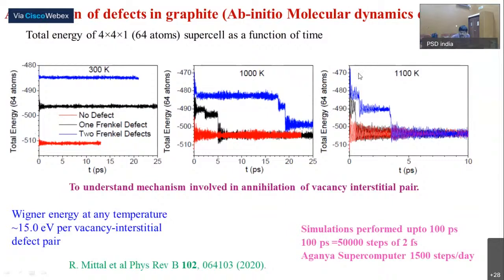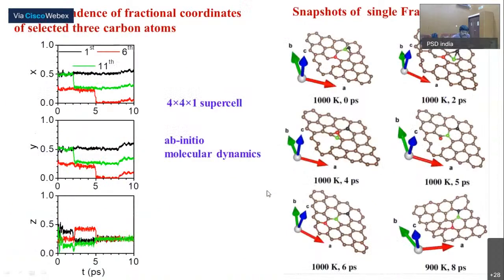But if we go to higher temperature, then this lattice with 2 Frenkel defects is also fully annealed. These calculations were performed using our Aganya supercomputing facilities at BARC, and all these results have already been published recently in Physical Review B. So to understand defect formation further, we have plotted here the time dependence of fractional coordinates of all the atoms.